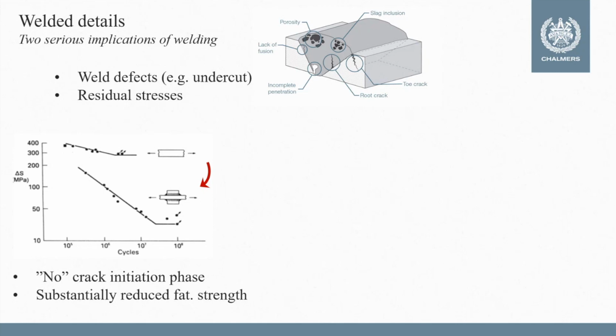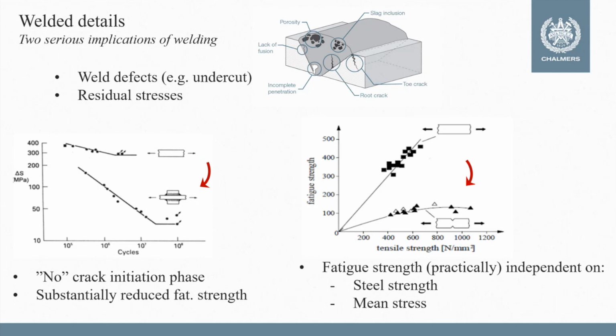And that's partly in principle due to the fact that we don't have crack initiation, or a very limited crack initiation phase. The second implication of that is that we also lose the dependency that we otherwise have in the base metal of the fatigue strength on the tensile strength. So if we are just looking at base metal performance without the influence of welding, we see that we have higher fatigue strength for higher strength steel.